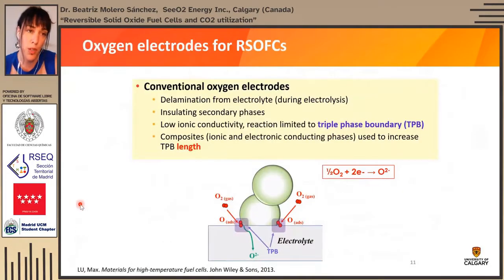So, for example, when using conventional electrodes and running them in reverse, several problems show up. Things like delaminating from the electrolyte, so that's physically delaminating the two solids during electrolysis. They can react and create insulating secondary phases. Or there's low ionic conductivity, and that makes the reaction limited to what's called the triple phase boundary. The triple phase boundary is this intersection here between the electrolyte and where the porous electrode meets, and that's where the electrochemical reaction is limited to.